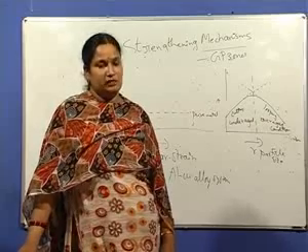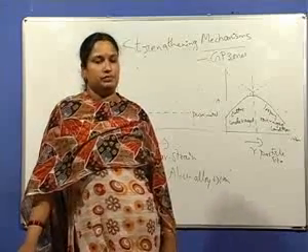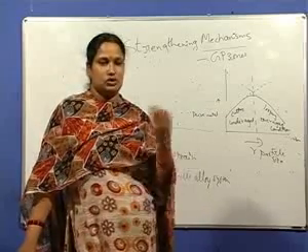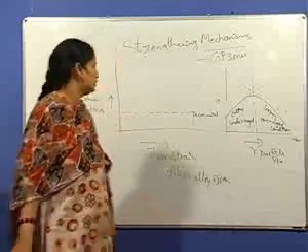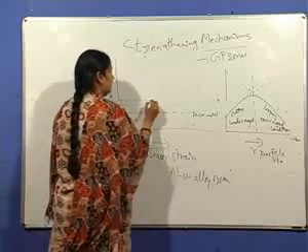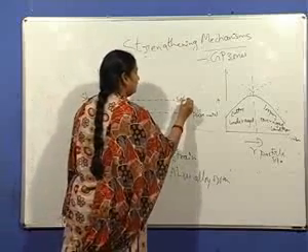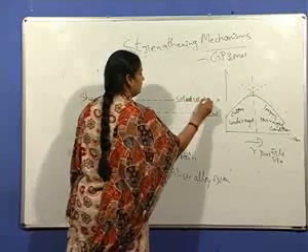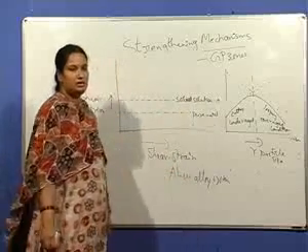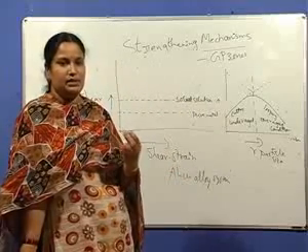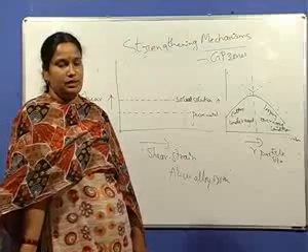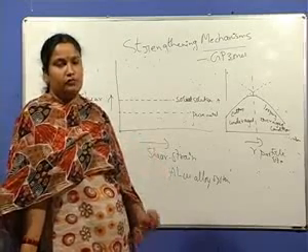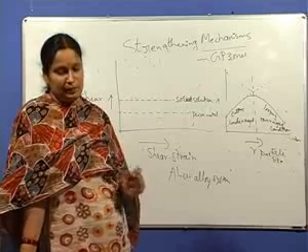Then for the case of solid solution, when the alloy is solutionized, all the solute goes into the solid solution, and it has higher yield stress than that of pure metal because of the lattice strains by the solute atoms. The next is the formation of the GP zones, GP1 and GP2 zones.